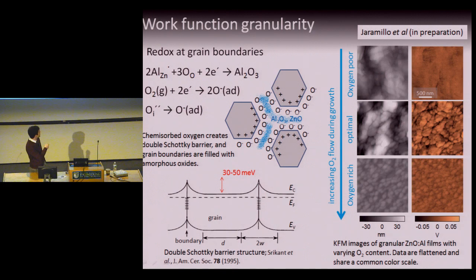What we're seeing here is this work function granularity is a representation of what limits the electrical conductivity of these materials, and what has been known for some time to limit the electrical conductivity of these materials, that is, electrons have a hard time hopping between grains. This actually gets at how you might start to optimize these materials for electrical conductivity.